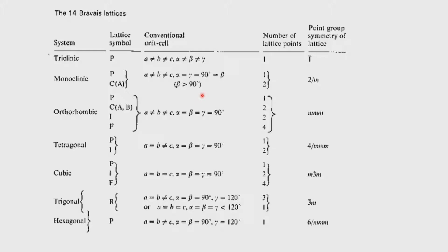Modern day crystallographers, particularly people who just solve structures without thinking about what is going on, even report beta angles less than 90, but crystallographic convention demands beta to be greater than 90. There are lots and lots of publications in literature, particularly by chemists practicing crystallography or somebody who takes crystallography for granted, or the mistake of the manufacturers and also the software people who have developed these packages. Beta is many times reported less than 90, but as a quality crystallography expert, one should always have beta greater than 90 degrees in a monoclinic representation. This is a must and people should take care of it.